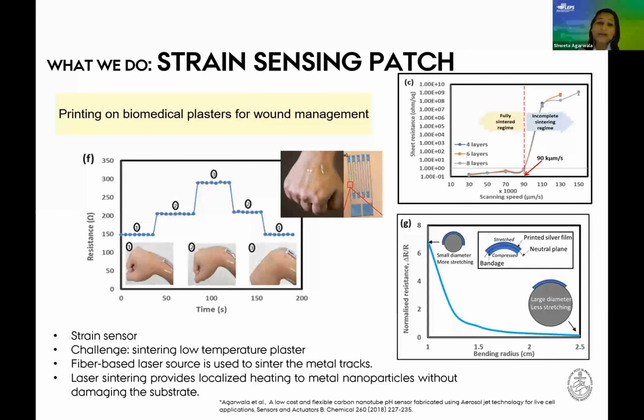Now, printing is one part of the story. Yes, we can print. That's not a problem because it's a smooth surface. It's a polymer like a plastic sheet. The problem comes from the fact that these are low temperature substrates. Most of the time when we are printing electronic inks, we need to have some kind of post-processing. Most of the time, this post-processing is a heat treatment, which is somewhere between 100 to 200 degrees. These substrates cannot withstand that temperature. And that is a problem. So what we did in this project was investigate laser sintering as a means of post-processing so that we could only sinter the tracks that we printed without damaging the underlying substrate.